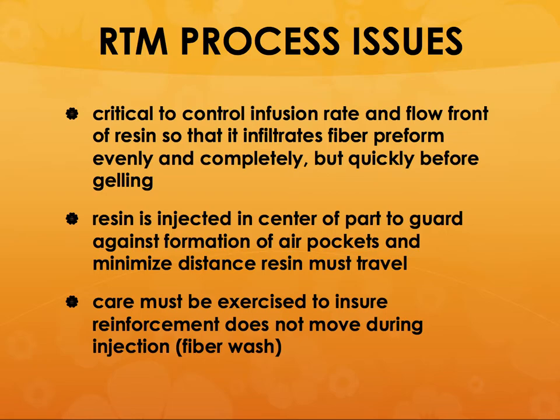So what are the critical issues for the RTM process? First of all, you need to control the infusion rate and flow front of the resin, so that the resin will infuse into the fiber preform evenly and completely, and before the gelling process starts. Typically, the resin is injected into the center of the part, so that you can minimize the distance that the resin must travel. And then you must take care that the reinforcement does not move during the injection process, so that the fibers don't move to one side and you have resin rich pockets.